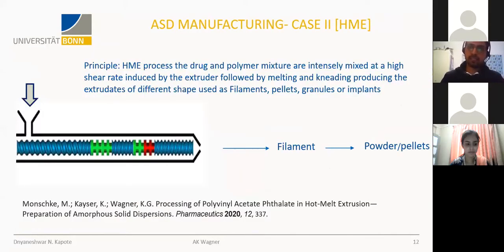Then the second case was with hot melt extrusion using shellac, same. So hot melt extrusion is widely known now in the pharmaceutical industry. It is a very evolving technique and very popular at the moment. So what we do in hot melt extrusion is we make a mixture, which I prepared previously. Then we have a feeder here, and from this feeder, the API-polymer mixture comes in contact with the conveying element here.